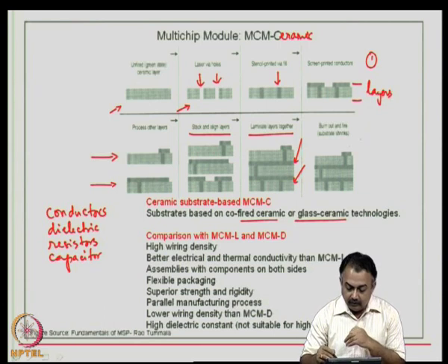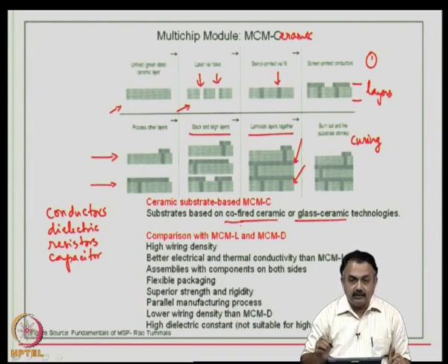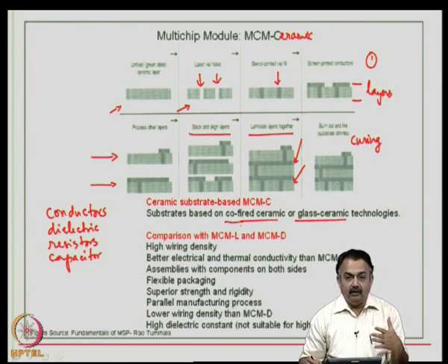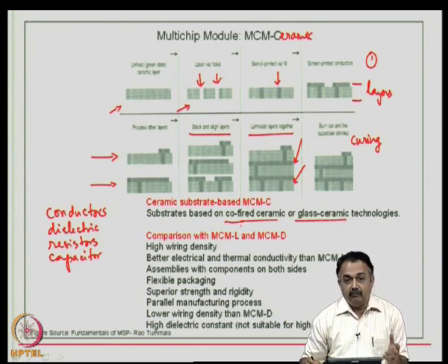Now, what you do is you do a curing process by co-firing. So, the word co-fire is used in this context of the green ceramic material and the conductors, in addition to other layers where you can have resistors and capacitors. These are co-fired at a particular temperature, and the actual properties are then obtained only after the firing process is completed. In a green state, the actual properties are not attained and there will be shrinkage. So, in the design stage, you have to give leverage for shrinkage of material.